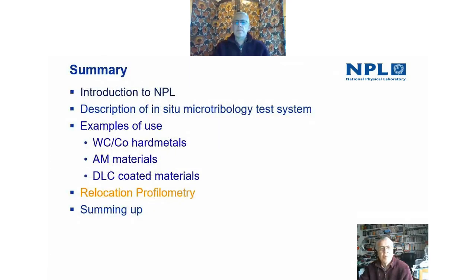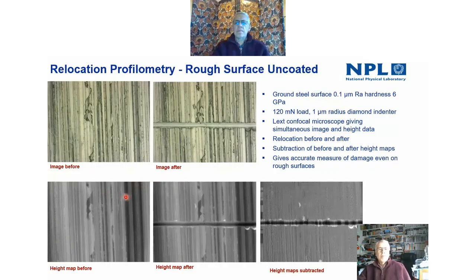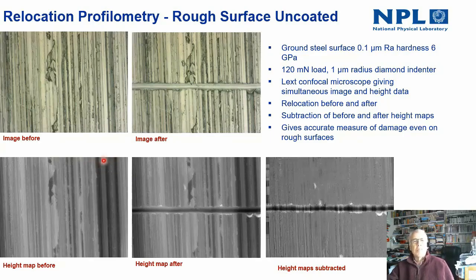So I just wanted to spend a few moments on relocation profilometry. This is an optical technique which is extremely useful, and this makes use of 3D optical microscopes where you get images as well as height maps. Here, what we've managed to do by careful practical work is locate an area before and after you've carried out a microtribology scratch. This is the image before on an uncoated sample, and this is the image afterwards. This is the height map before and the height map afterwards, and you can then combine and register the two height maps and subtract the one from the other, and this dark area here is the actual volume of the scratch itself without any contribution from the original rough surface, and that's extremely useful.